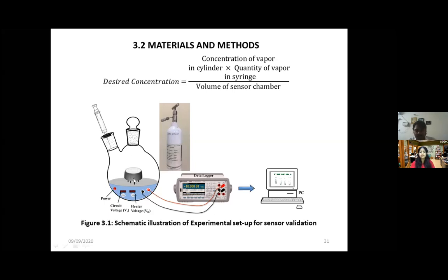All the sensors have been individually placed here. This is just a schematic illustration. All the 4 sensors have been placed. And this is an acetone pre-calibrated cylinder purchased from Chemtron Science Laboratories in New Delhi. So the desired concentration can be achieved based on this formula. So concentration of vapor in cylinder. The concentration is 5000 ppm of acetone in a 500 ml cylinder here. So concentration of vapor in cylinder, that is 5000 ppm, into quantity of vapor in syringe, 2 ml, 3 ml, 4 ml, like that, and volume of sensor chamber. This is a 250 ml sensor chamber volume.